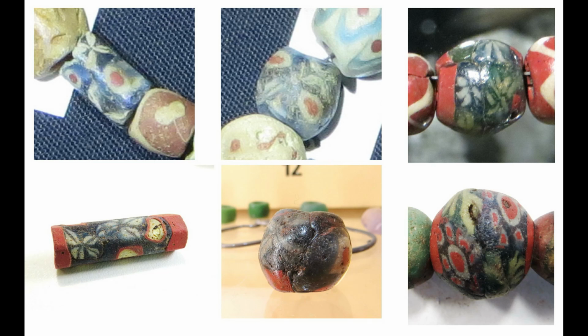For this paper, I will concentrate on the mosaic beads made using millefiori as decoration, and here are some examples found in Britain. They seem to have first appeared in Hellenistic times and are decorated using slices cut from pre-made glass rods that have patterns running through their lengths. These pattern rods are called canes and require considerable skill to make.